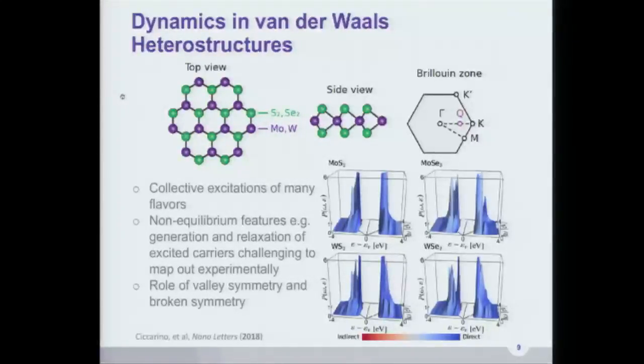And what's exciting about these TMDs is that you can make them, of course, in monolayer form, and you can make mixed layers of these. So you could have a layer that is a molysulfide, another that's a molyselenide. There are different permutation combinations you could do. And in that stacking, you could start to explore some of the questions where I said that the interlayer interaction changes the in-plane behavior and could fundamentally lead to new kinds of physics. So my student Chris Ciccarino, who's sitting up here, published a paper on this with me in Nano Letters earlier this year, where we found that there's actually a set of relaxation pathways, in particular the lifetimes for these, far from equilibrium, that were poorly understood.